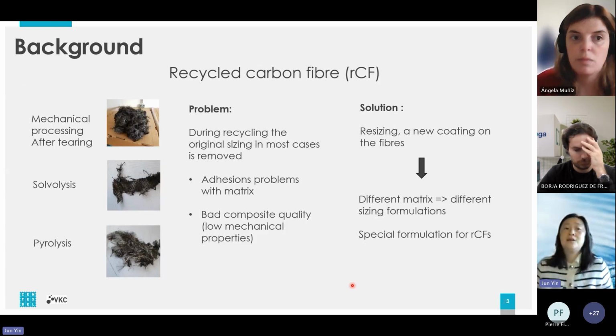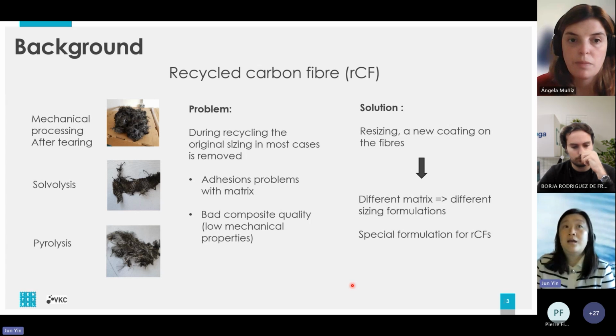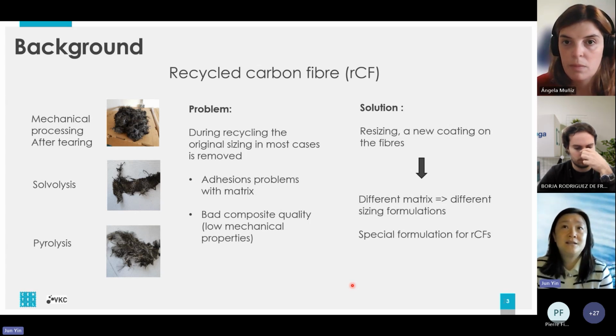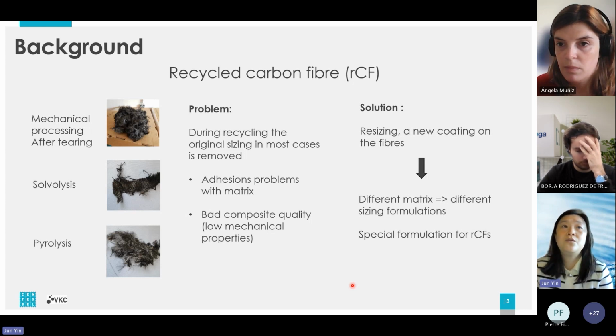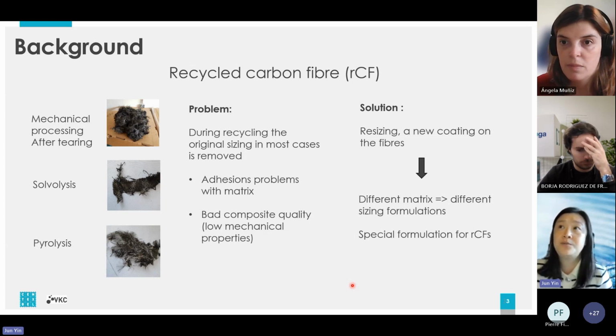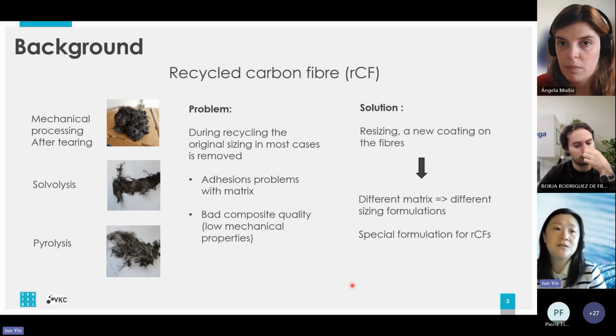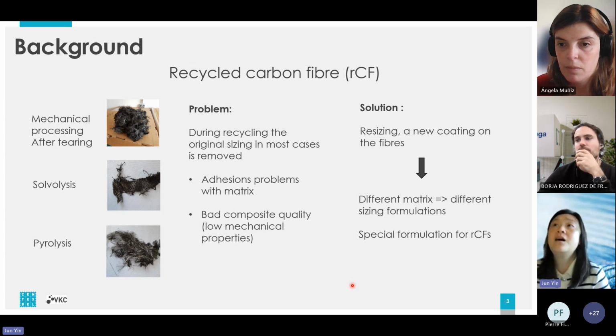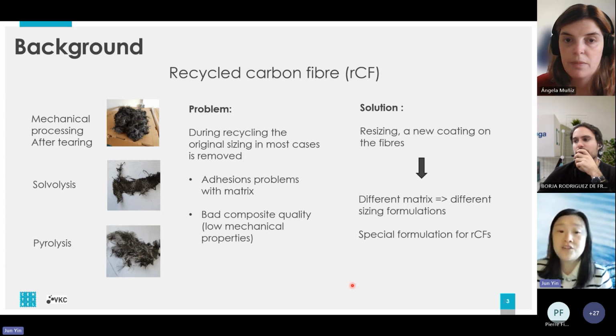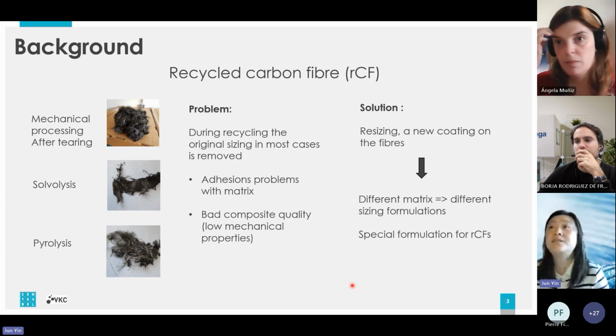So during the recycling process, solvolysis or pyrolysis, the original sizing in most cases is removed. So when we want to reuse this recycled carbon fiber, there's also a problem of adhesion with the matrix, and so it leads to bad composite quality. That means low mechanical properties. So the solution in this project is that we want to apply a resizing formulation, a new coating, on this recycled carbon fiber. But there are some challenges.